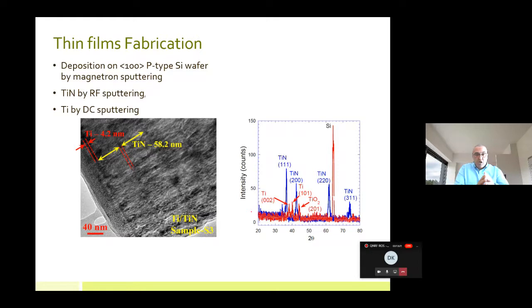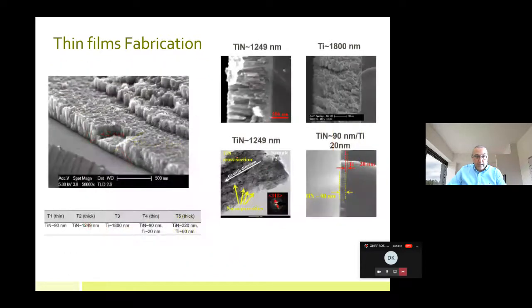So one part of the project was the materials fabrication, and I'm happy to report that by year 3 we were able to successfully produce a lot of thin films with good control over the periods, and that allowed us to do our study, which I'm going to talk about in a little bit. This SEM image basically shows the alternating layers, and you can notice how we can control the periods and the thicknesses involved.